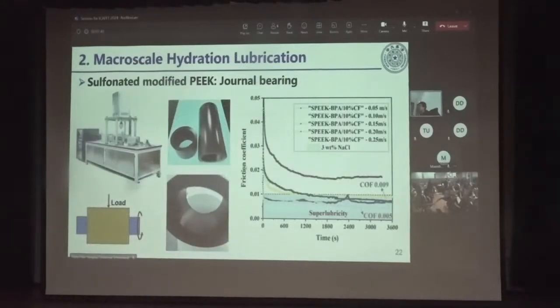And then finally, we fabricated journal bearings with the sulfonated modified PEEK and tested it by the journal bearing test machine. During the test, the bearing was lubricated by salt solution, and we can find the friction coefficient decreased to less than 0.01. After the test, we can find almost no wear on the surface. In other words, the wear of the bearing is quite small. So this is a very good material to make journal bearings.